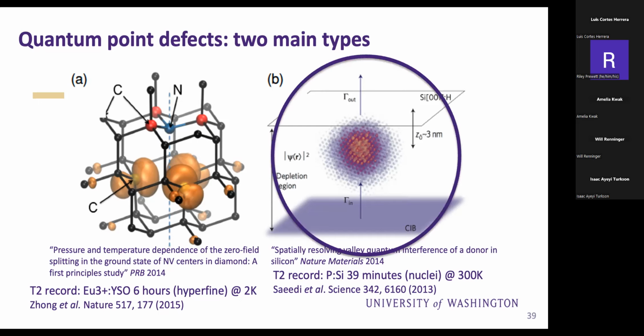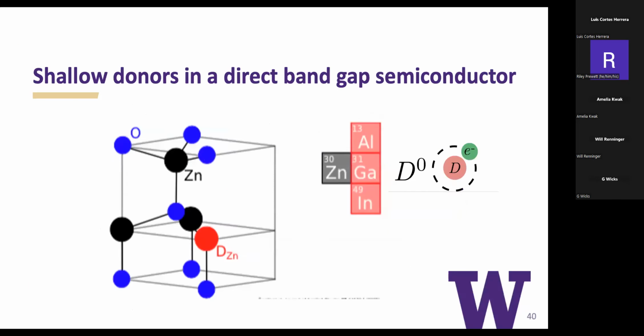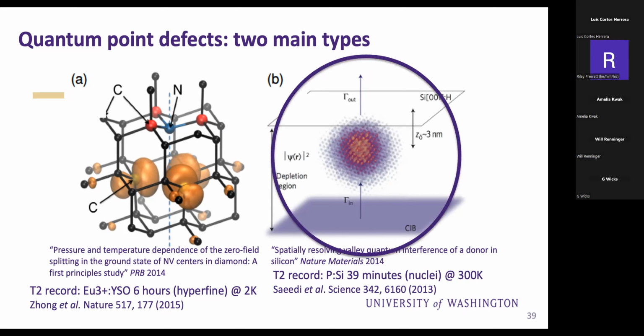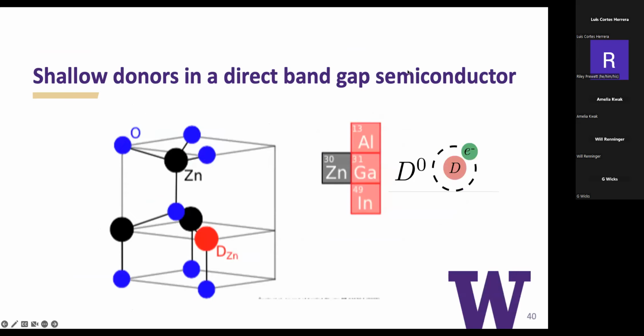The second half of my talk, or I would say the last 5 minutes of my talk, is going to focus on these extended defects, which are studied much less than the deeper defects for quantum network applications. Silicon doesn't have an efficient optical interface. And so we look at shallow donors in direct bandgap semiconductors, such as zinc oxide, where aluminum, gallium, or indium can substitute for the zinc, providing that extra electron, which at low temperature is bound coulombically to the donor impurity and creates a giant hydrogen atom in your system.